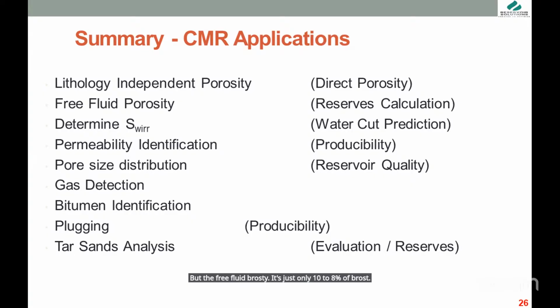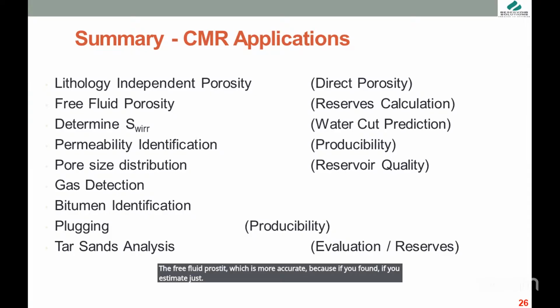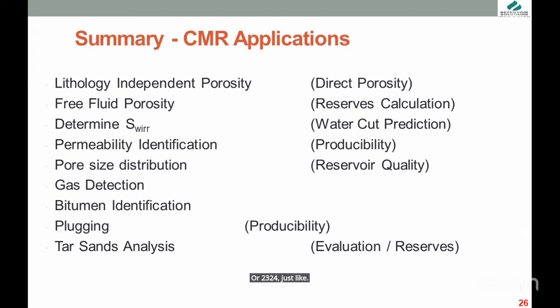In this case, when you make the volumetric estimation, you will get the free fluid porosity, which is more accurate, because if you estimate just from neutron density calculation, you will get 25 or 23, 24, without separating the capillary bound and free fluid. Your reserve estimation will depend on 25, but the actual free fluid is only 10 or 11. This is the actual porosity of your free fluid that you can produce from your reservoir. So this is one of the most important effectiveness of the NMR application.